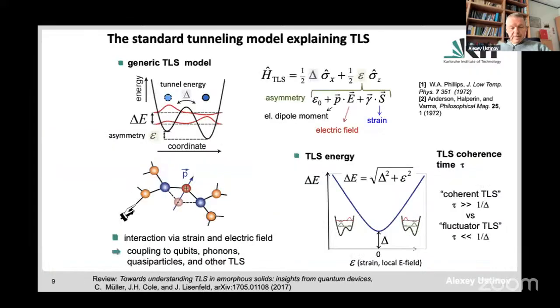And these defects actually first were speculated back in the beginning of the 70s. About that time, people started looking into disordered dielectrics, glasses. And the glasses have shown very significant deviation in their properties at low temperatures. And these properties were basically showing that there are additional degrees of freedom which contribute to storing the energy in these materials. For example, specific heat was much larger, by orders of magnitude larger than in crystalline materials. And simultaneously, there was a model which is now called the standard tunneling model, explaining two-level systems, TLS. This model was proposed simultaneously by Phillips and P.W. Anderson with colleagues,